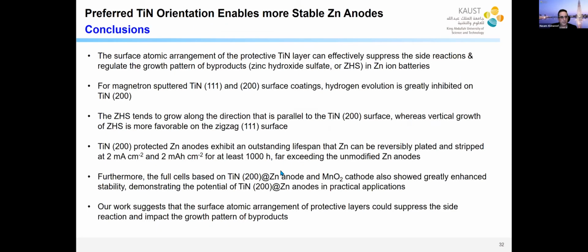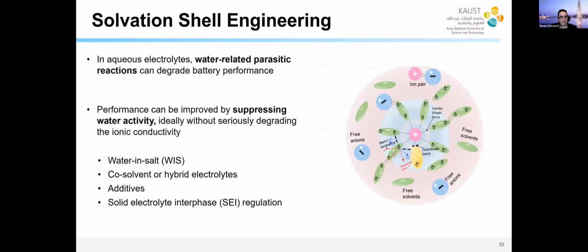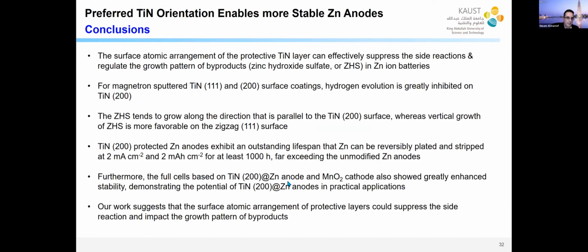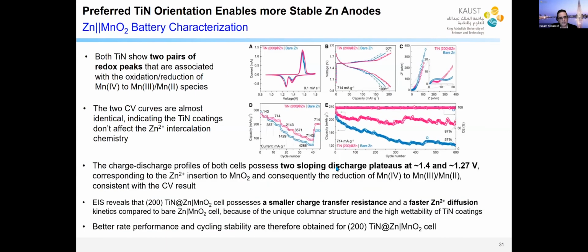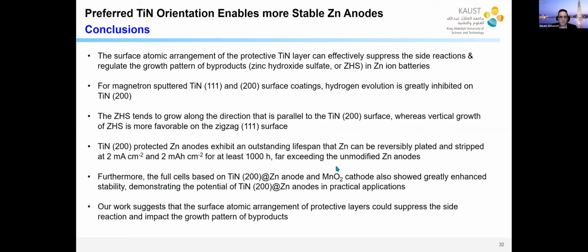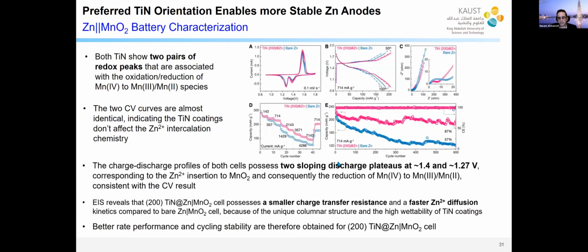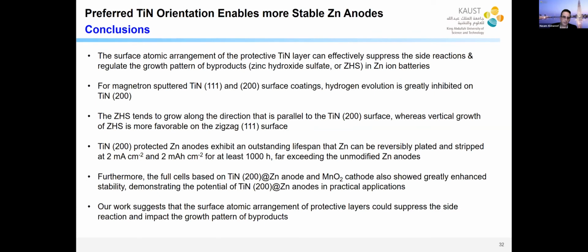So then, to try to explain, I think I intentionally or unintentionally may have deleted the slide that shows the model. Actually, we did DFT simulations and we showed that the root cause of this effect is that the growth of this ZHS phase on the 200 direction or plane of the titanium nitride is energetically costly. Basically, it requires energy input.